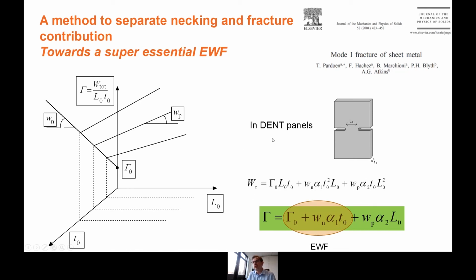And as a matter of fact, what you find is that the work of necking, the total work of necking, is proportional to thickness. And why is that? The work of necking scales with the volume of the neck. And the volume of the neck is increasing with the thickness. And so it's proportional, it depends on thickness. And if you take the work of necking per unit area, what you find is that you will have a scaling with respect to the thickness.